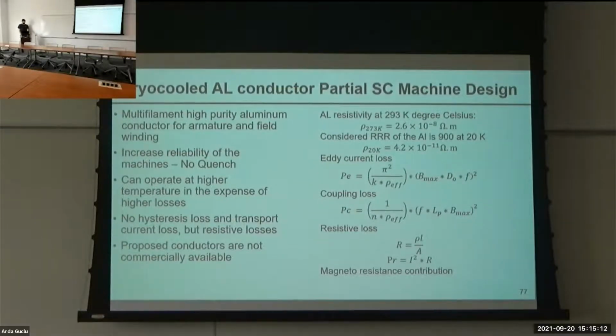In this design, we would have the aluminum conductor for the armature and field windings. The advantage of this is that since the aluminum wouldn't be superconducting, there's no chance of a quench, and it can operate at higher temperatures at the expense of higher losses. And while there's no hysteresis loss and transport current loss, there are resistive losses since it wouldn't be superconducting. Another disadvantage is that they're currently not commercially available. So this is really only for a theoretical or proposed aluminum conductor.